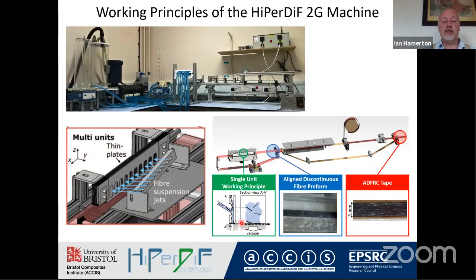And so what happens is we then end up with a series of discontinuous fibers, aligned and consolidated into an aligned discontinuous fiber preform. So at this point, we've got essentially a dry tape, highly aligned, short discontinuous fibers. That's then dried, combined with a matrix, and at the end of this, we produce a tape, a pre-preg tape.